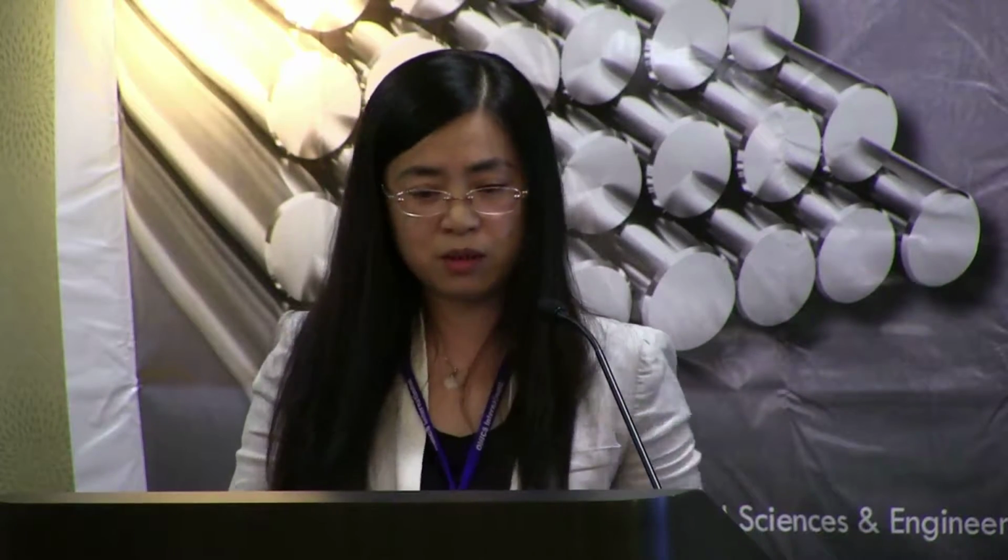So we use this method to fabricate fibers with different-size spindle knots. We call this the spider knot, similar to wetted spider silk. We found that the different-size spider knots can be controlled by different pH, and each spider knot has a different gradient. So we use this method to fabricate different-size spider knots, similar to spider silk.